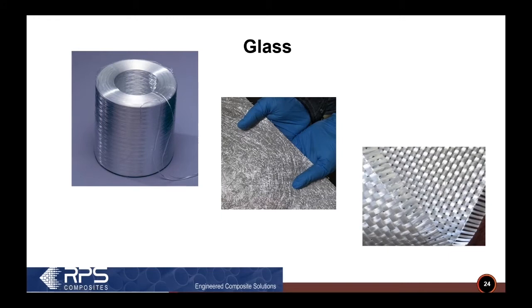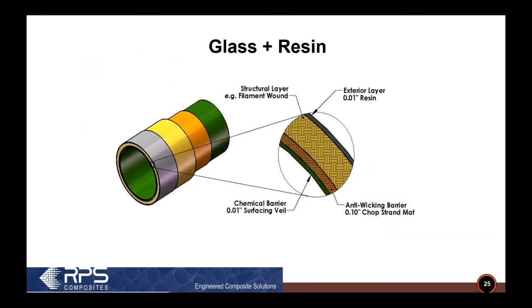However, you only get about 25% reinforcement when you saturate it with resin. So another way to reinforce the fitting is to use a woven roving. I've taken the glass roving and woven it into a matting, like you can see on the right-hand side, and that sheet material, which is woven roving, can be used to reinforce larger fittings.